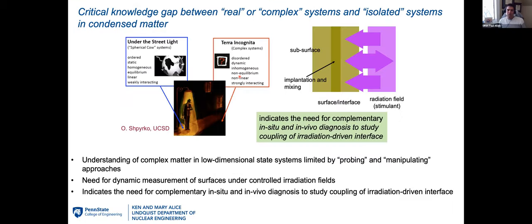But one challenge that comes right away in being able to manipulate these material surfaces in an effective way is that we would like to understand how the surface and the interface with our radiation field, in this case, the stimulant, for example, the energetic ions that emanate from a plasma, how that interface is evolving in time. And this is quite different from the conventional approach in materials design, where we have isolated systems that are organized, equilibrated. We are trying to probe a very shallow depth of atoms, anywhere from a monolayer to a few nanometers. We need to be able to probe that depth while we're doing the irradiation.